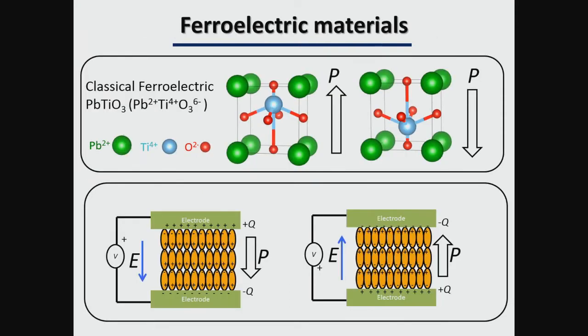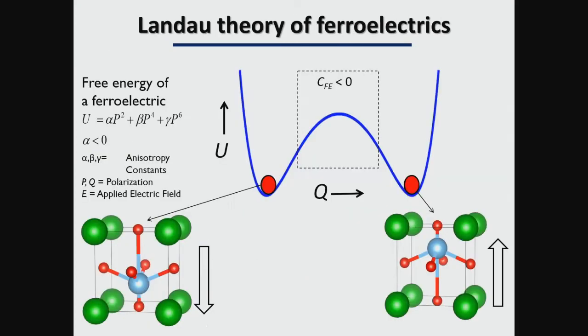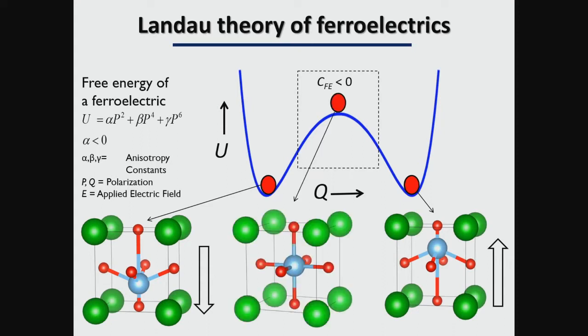Let me give a brief overview of ferroelectric materials. In the unit cell of a ferroelectric material, the central atom is not at the center of symmetry — it's slightly off-centered — and this off-centering gives a spontaneous polarization without an electric field, in either direction. The defining factor of a ferroelectric is that you can switch the direction of polarization by applying an electric field larger than the coercive field. The two minima of the double-well energy landscape correspond to the two directions of spontaneous polarization, and for negative capacitance the unit cell should be symmetric.